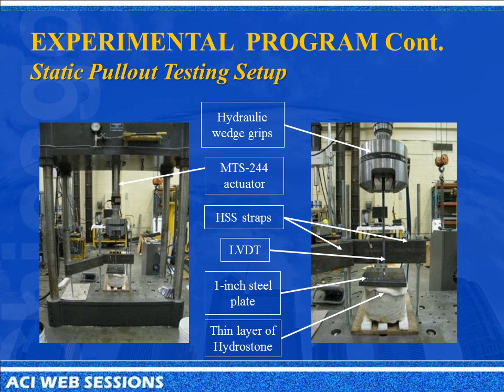For our static pullout testing, we did the confined pullout testing. Testing was done in a four-post testing frame with an MTS actuator with a 500 kilonewton capacity and 20 inches of stroke. We did apply a thin layer of hydrostone between the steel plate that you see at the bottom here for the confinement, just to ensure full contact between the surface of the specimen and the steel plate and a uniform distribution of the load on the specimen. So that's a typical specimen just prior to testing.